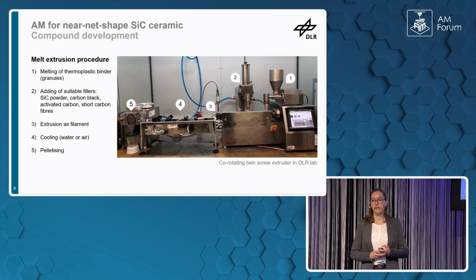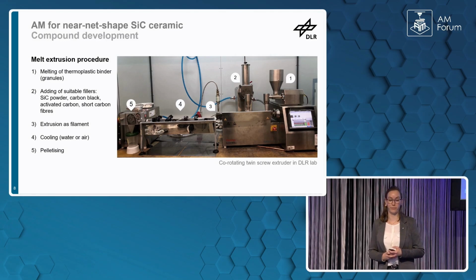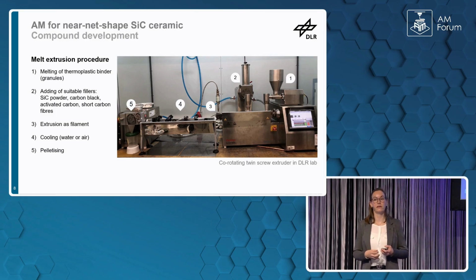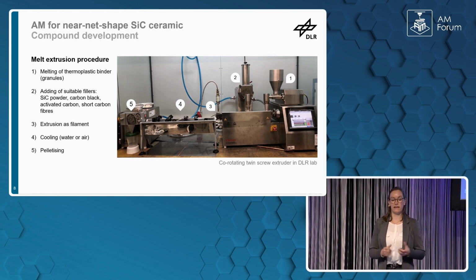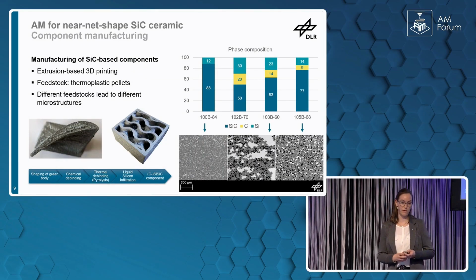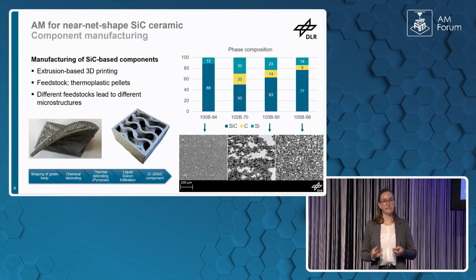For the 3D printing at DLR, we use a pellet-based printer. First of all stands the compound development. Granules of thermoplastic binder are melted, and suitable fillers like carbon black, silicon carbide powder, activated carbon, or short carbon fibers are added. All the components are mixed in a twin screw extruder and then extruded as a filament, cooled in water or air, and cut into pellets. For the component manufacturing, these compound pellets serve as a feedstock for the extrusion-based 3D printing.